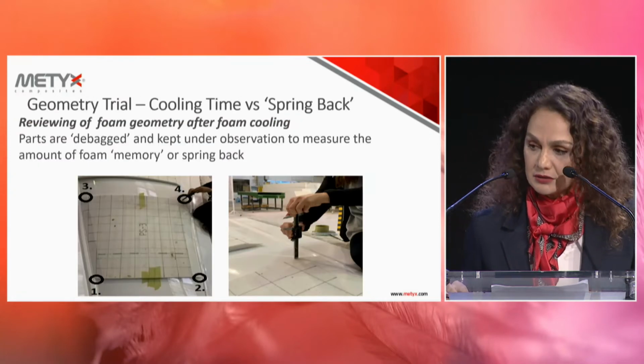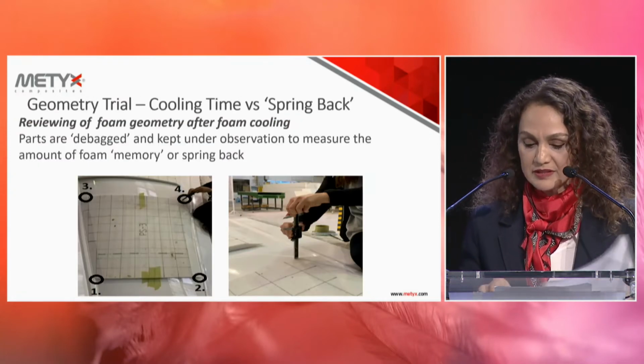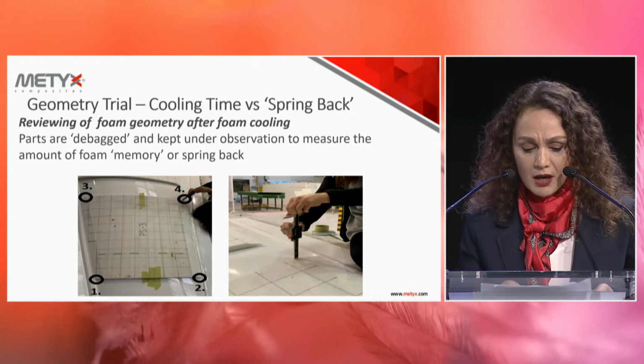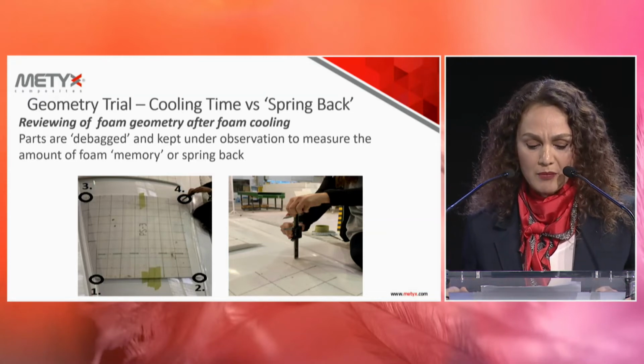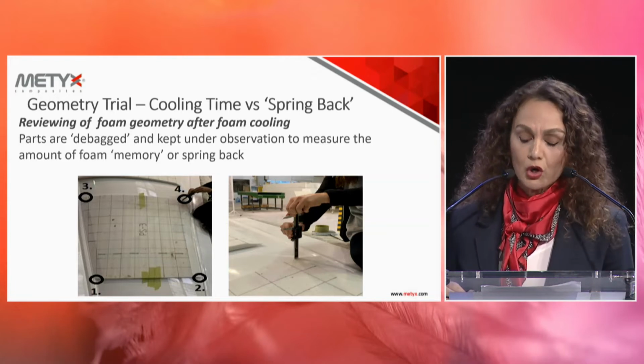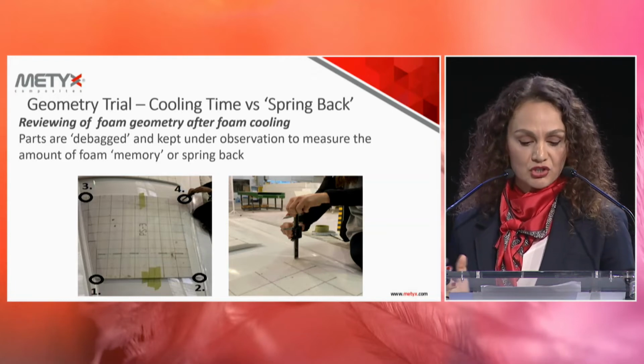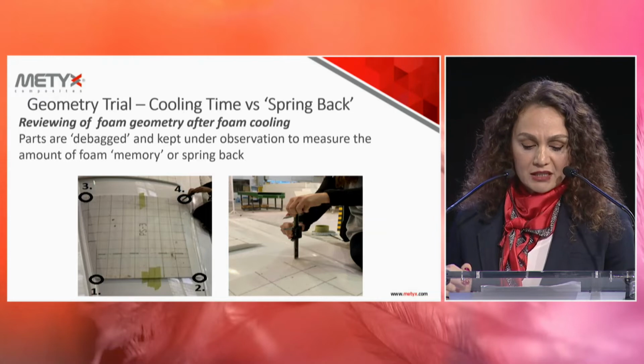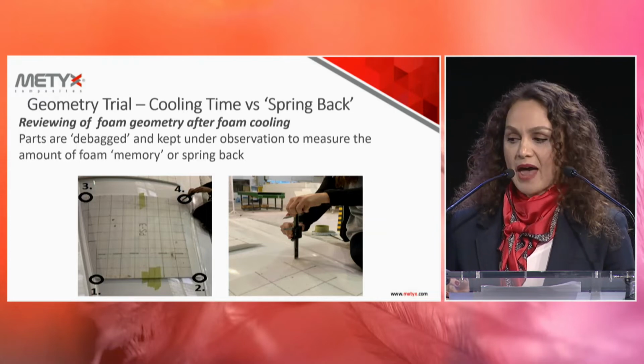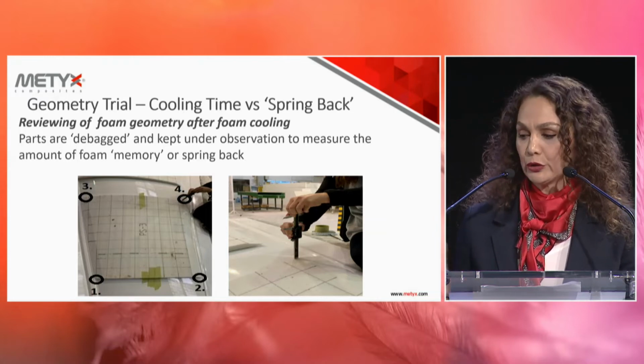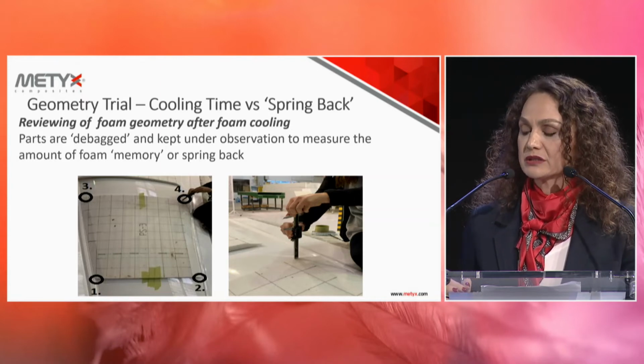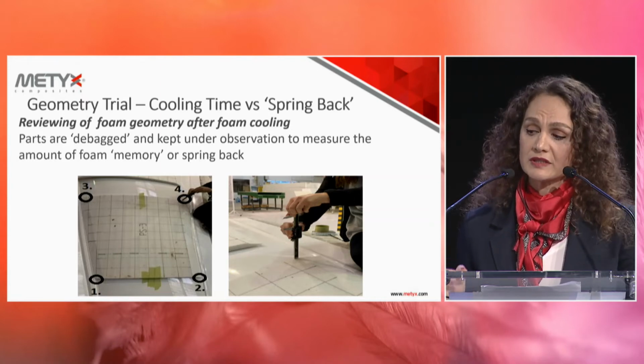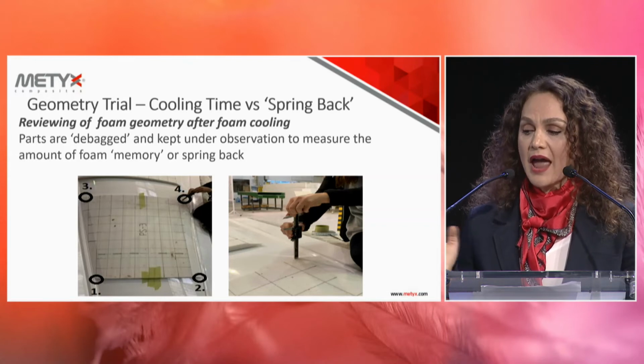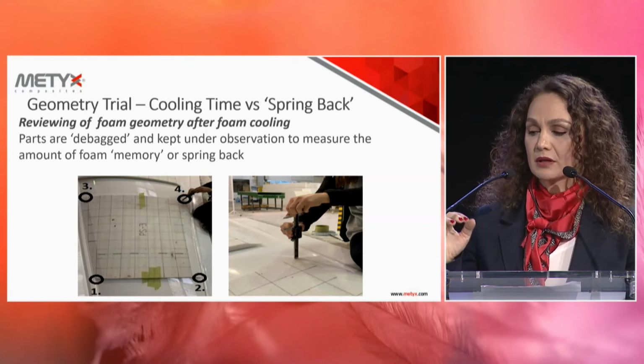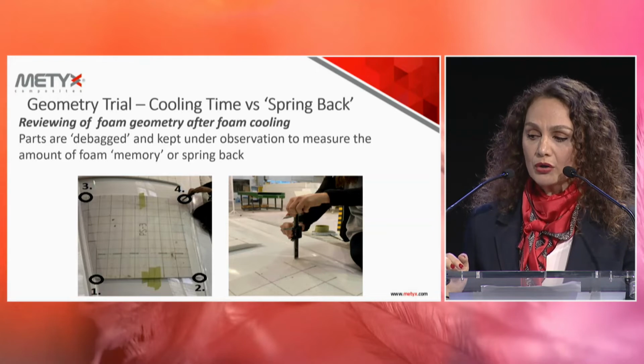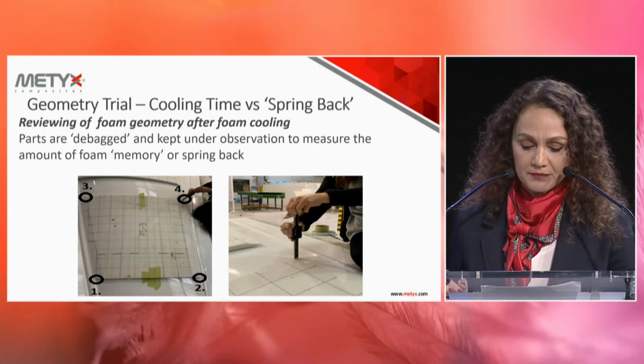The other measurement was the spring back. Spring back is what we call the memory of the foam, what it wants to return to its initial straight position. Basically, we measure the foam after cooling on the mold. After we remove the vacuum bag, we measure the distance between the mold surface and the edge of the core at 4 points.